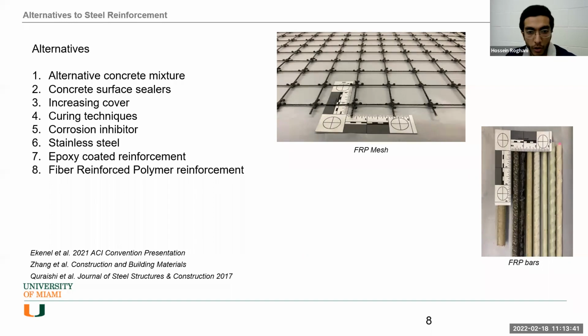In addition, increasing the concrete cover makes it take longer for the chloride to reach the steel, because you have a very thin layer on top of your steel reinforcement, which is not stable in the presence of the chloride. So when the chloride goes inside, you lose that thin film on top of your rebar, and the rebar will start to corrode. If you increase the cover, it takes longer for the chloride to reach the steel reinforcement, but the penetration of the corrosive substances depends more heavily on the crack width than the crack depth. So even if you put your rebars at a lower level, at the end of the day, you still have the corrosion, maybe 1 year later, maybe 2 years later, but still you have it.